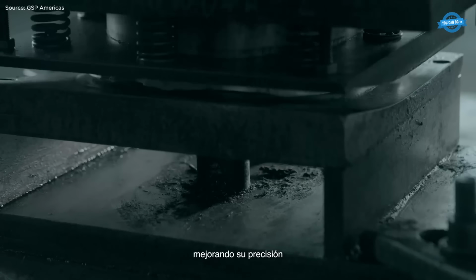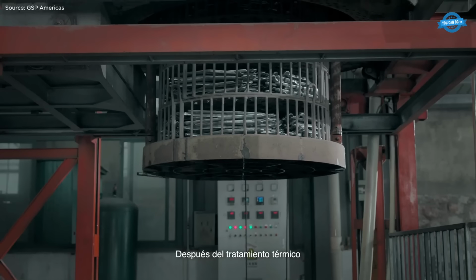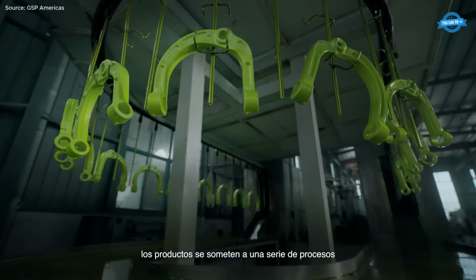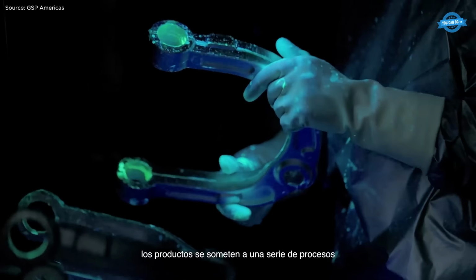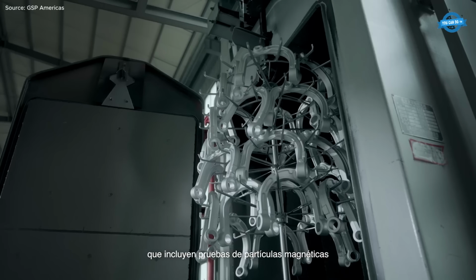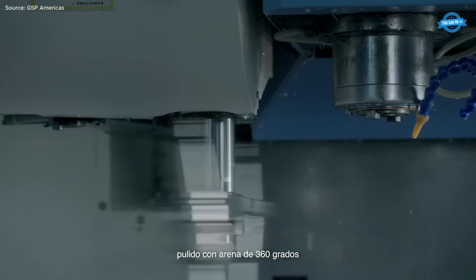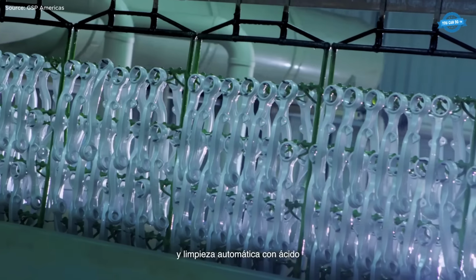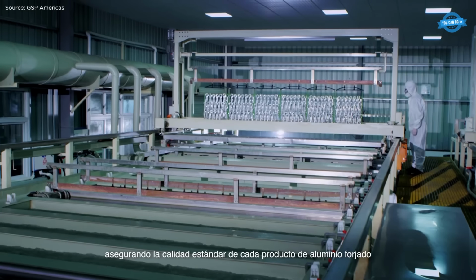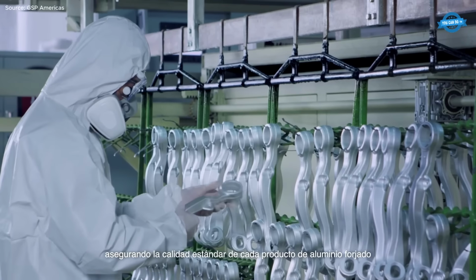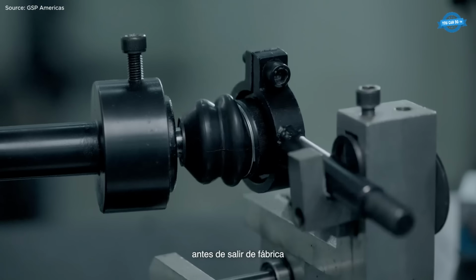For aluminum control arms, production relies on multi-stage automated forging using high-capacity presses, followed by heat treatment, magnetic particle inspection, surface polishing, and automated acid cleaning. Each component undergoes functional and dimensional testing before release, with process data fed back into upstream manufacturing stages to support continuous technical optimization.